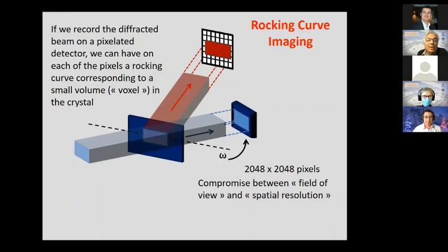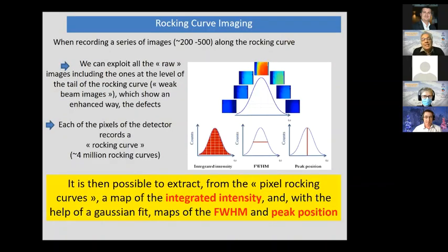As we have 2048 by 2048 pixels on the detector, we have to do a kind of compromise between field of view and spatial resolution. For instance, if your pixel is 1 micrometer, you have about 2 millimeters by 2 millimeters of field of view. And if you want a bigger field of view, you have to have a larger pixel size. So that goes to rocking curve imaging.